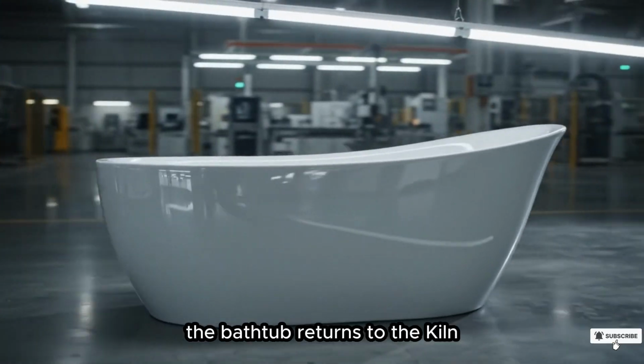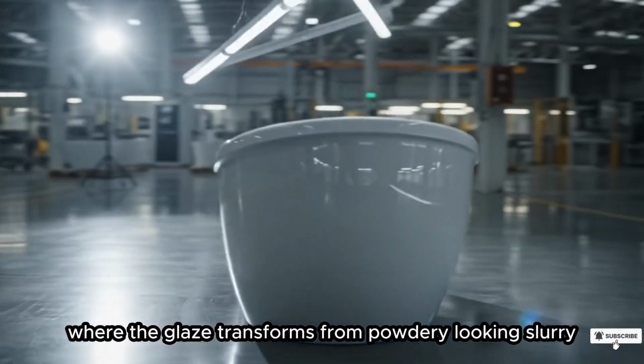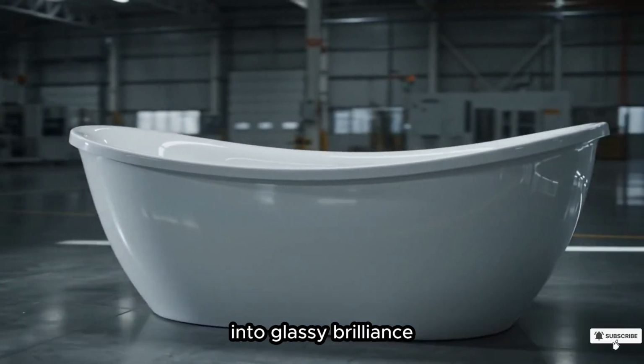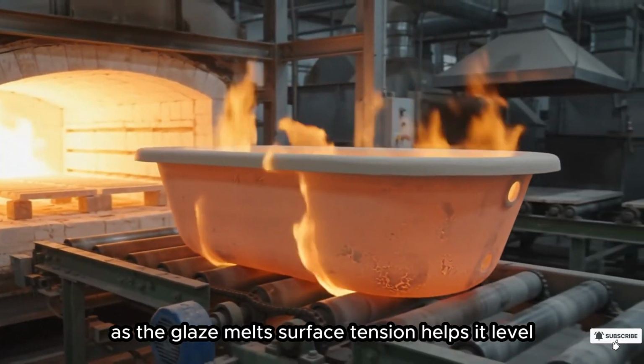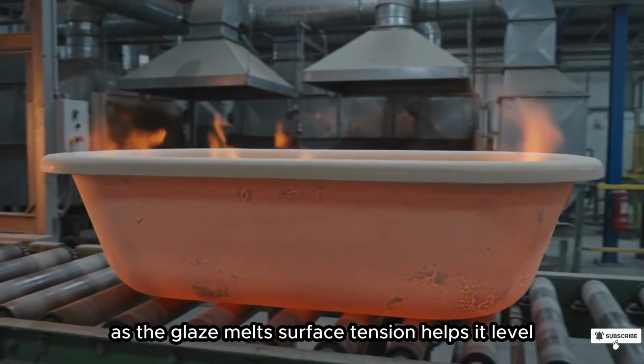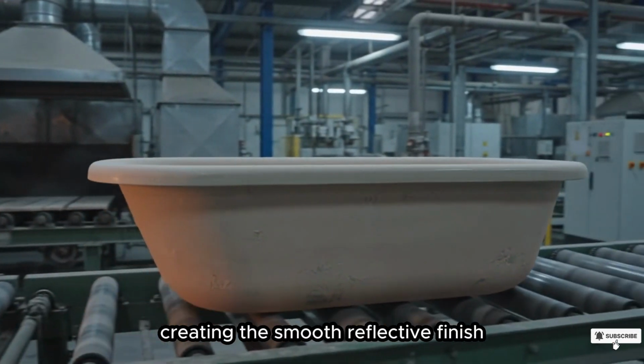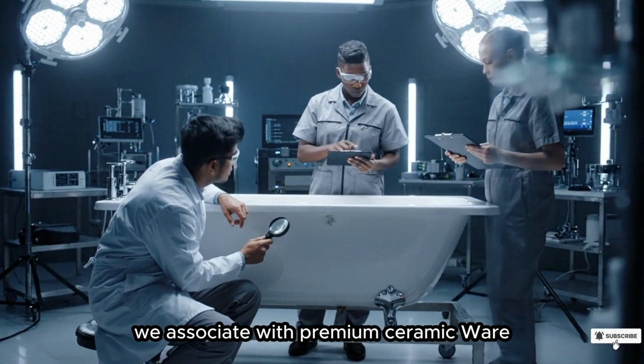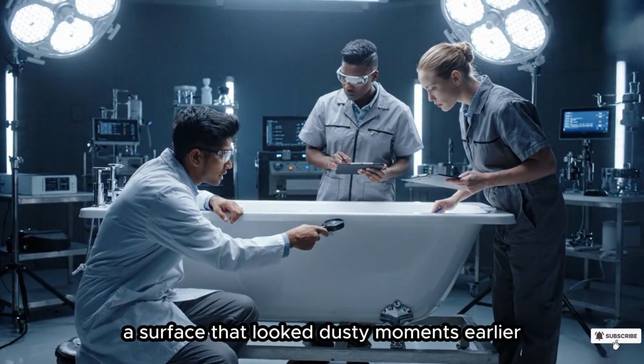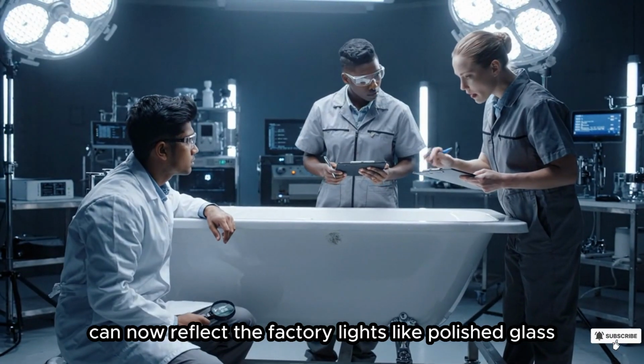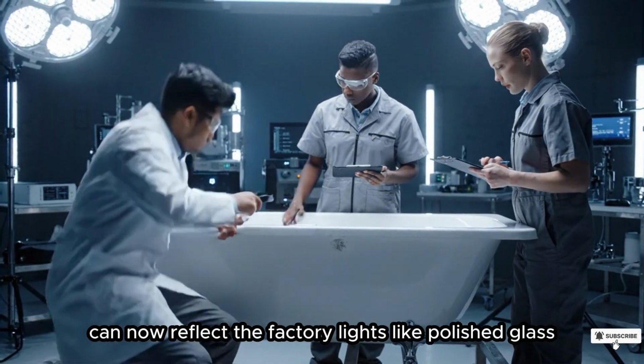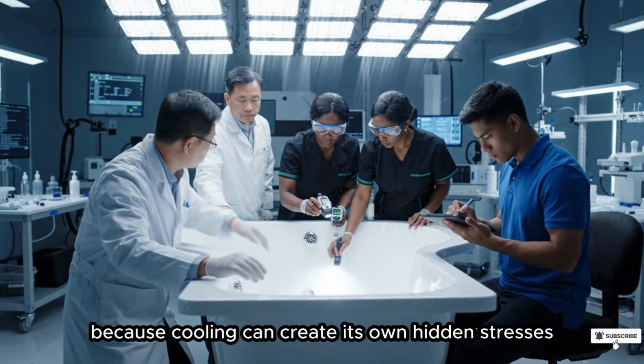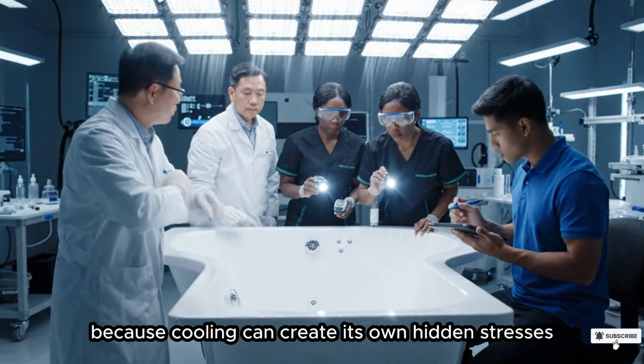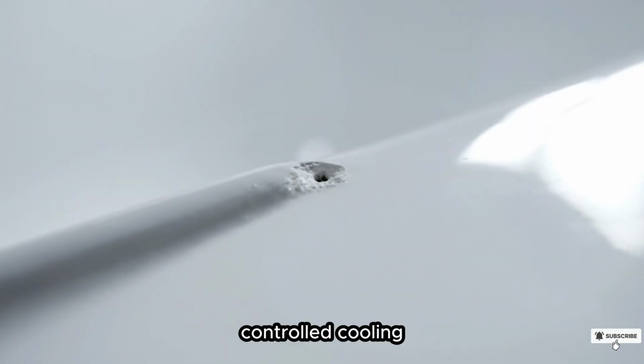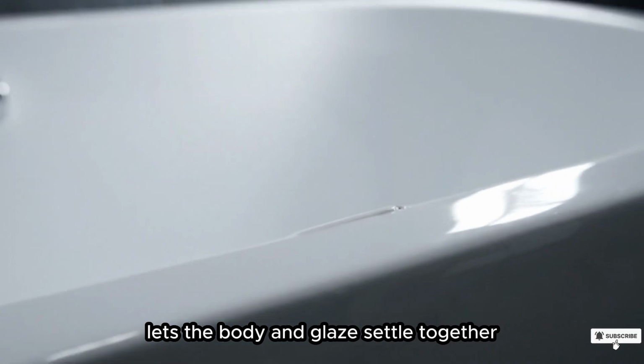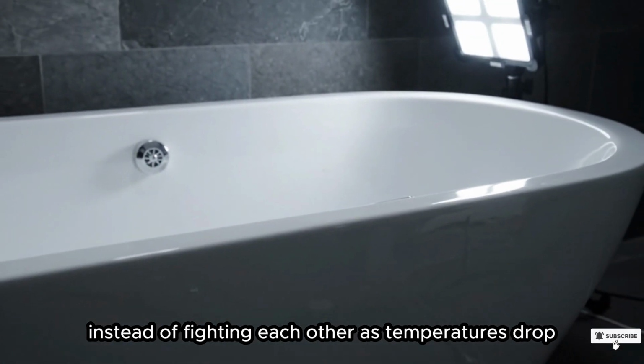After coating, the bathtub returns to the kiln, where the glaze transforms from powdery-looking slurry into glassy brilliance. As the glaze melts, surface tension helps it level, creating the smooth, reflective finish we associate with premium ceramic ware. And here's the payoff. A surface that looked dusty moments earlier can now reflect the factory lights like polished glass. But the journey is not over, because cooling can create its own hidden stresses inside the ceramic. Controlled cooling lets the body and glaze settle together instead of fighting each other as temperatures drop.